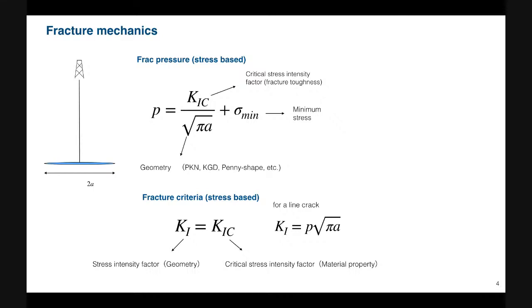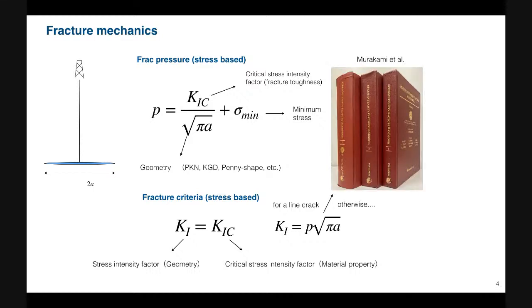And if the crack is not this simple geometry, how do we get the stress intensity factor? There's a handbook with three volumes. We can hope to find the stress intensity factor we're looking for in this handbook, hoping that someone has worked on it before, or we can compute it numerically. But if you start thinking about many realizations of fracture propagation, this computation becomes very costly. So this is one reason, not the only one, that it is often convenient to impose some restrictions on the fracture propagation path. It's not a theoretical limitation, but there are practical reasons to do it.